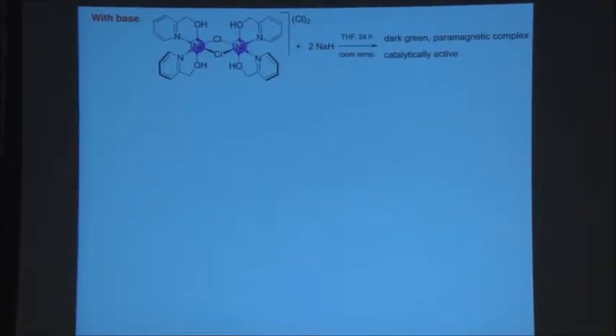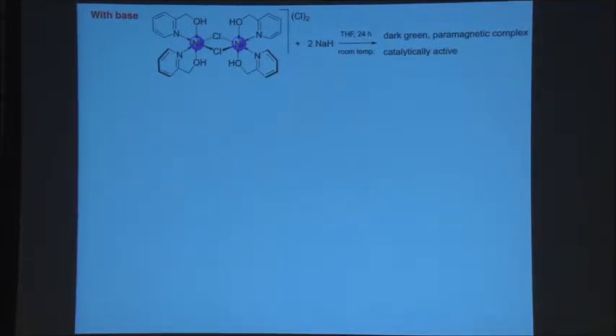Now, in the presence of base, as I said before, you may be able to fine-tune the properties because you change the electronic density at the metal center. You have a metal which is going to be more electron-rich. And also we had realized at an early stage that this compound is not very soluble. When we ran our catalysis in toluene or chlorobenzene, not very soluble. So I thought maybe if we could transform this ionic structure with the two external chlorides, you know, they are hydrogen bonded, but still they are not ligands, they are counterions. If we could just deprotonate two of the alcohol functions and remove two equivalents of HCl, we would form a neutral species. And this neutral species might be more soluble in toluene. And that may be a bonus for the catalysis, because we are performing the catalysis in these sorts of solvents.